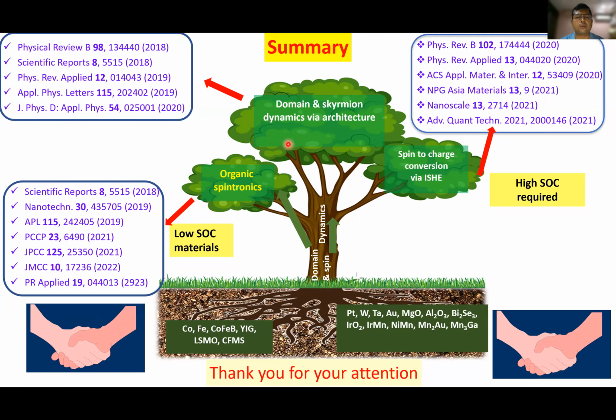Oh, very nice question. Actually, I didn't have time to go into the details, but if you look at those papers, what we say, or what even some other people have found, of course they don't do much on the domain structure or magnetization study, but primarily it has been shown that there is an interfacial hybridization between the carbon and the ferromagnetic elements. And there is also some amount of charge transfer, because of which the carbon gets a magnetic moment.